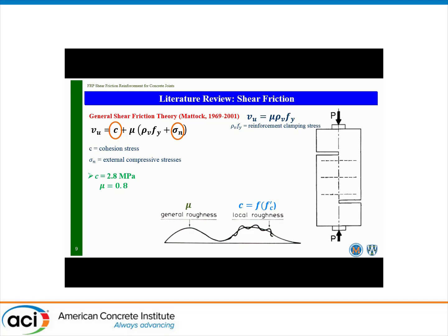This contribution of the concrete arises from two sources: cohesion, which, if we imagine a close-up of the rough surface of the concrete, comes from the local roughness as the main source; and the general roughness, where the reinforcement activates and ensures there's no big gap so the two surfaces still interact together. This will contribute collectively to the shear strength of that interface.